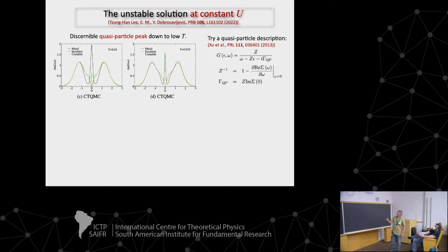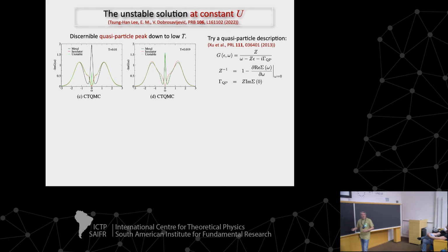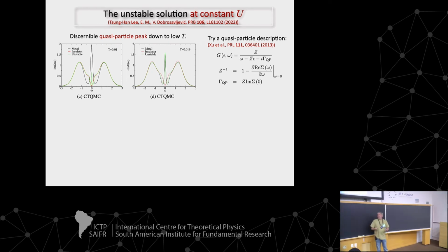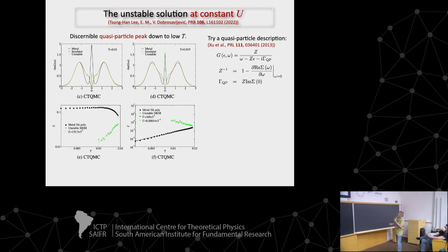You have a quasi-particle residue. In a Fermi liquid, this is a constant. And you have a scattering rate that in a Fermi liquid should go like T squared as a function of temperature. This is a normal metal. So if you look at the metallic solution, Z goes to a constant, gamma has a T-squared behavior, as you would expect. But now if you look at the unstable solution, Z actually decreases to 0 as a power law. Very, very strange, not a Fermi liquid.